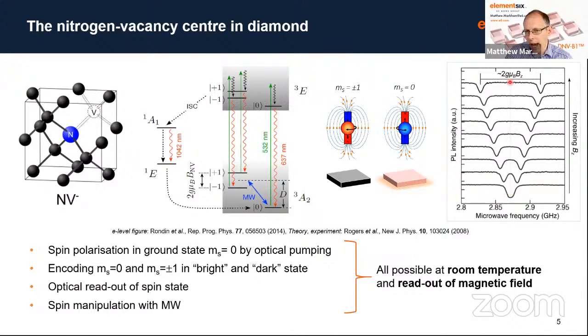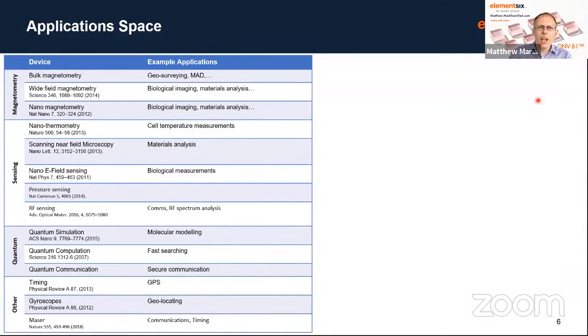And as we apply magnetic field, these two energy levels here, which are degenerate at zero field, split according to a Zeeman interaction. And you can obviously, for things like magnetic sensing, extract out what the magnetic field is. And I think what's really exciting is you can do all of this at room temperature. So this has led to lots of different applications.